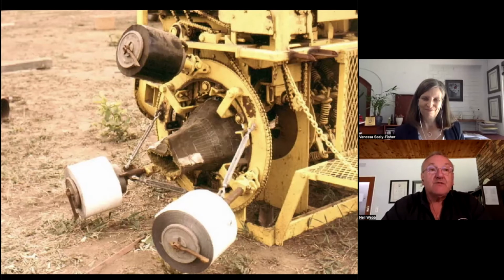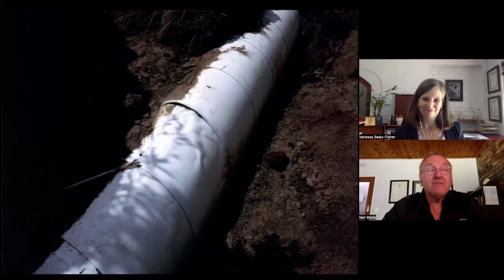Even machines don't always get it right. If you don't set up the machine correctly, you'll end up with an offset in either the spiral or the tension or whatever, and you'll end up with these huge gaps in the tape where you can then get water ingress and the possibility of corrosion in spite of the presence of cathodic protection that might be on the pipe.